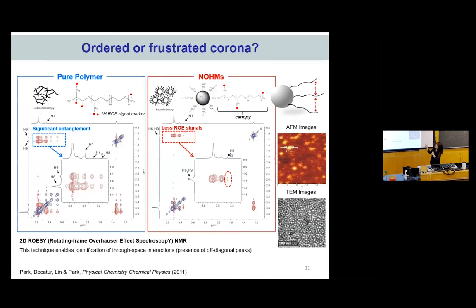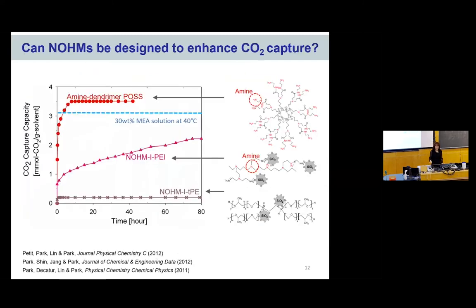So what we found out was by doing so, we created a lot of something called free volume between polymer chains so that we were able to jam pack CO2 a lot more differently and also had a better accessibility of all the functional groups we wanted to have between. So the only thing we had to do now was we just need to decorate all these polymer chains with amine, which loves to grab on CO2. And that's what we did. So as you can see, each time we add more amine functional groups along the polymer chains, we got much more CO2 loading per gram of the material, as expected.